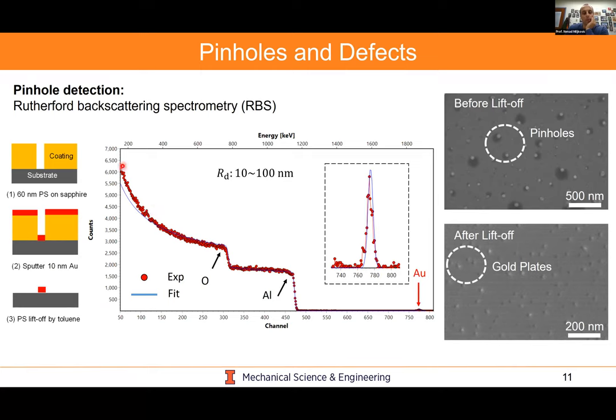And what you're seeing here is the spectra looking at oxygen, aluminum, and indeed we get this gold peak, saying that we have gold platelets or clusters left that are there because the pinholes have been filled and deposited. And this again is an SEM, this is before liftoff and after liftoff on a silicon wafer. You could see these dense pinholes that are left over as proof of our hypothesis.